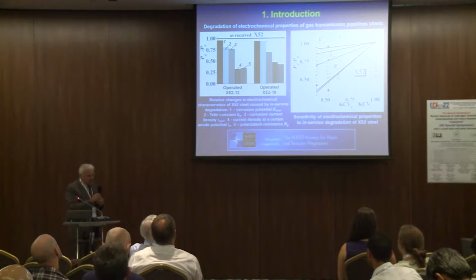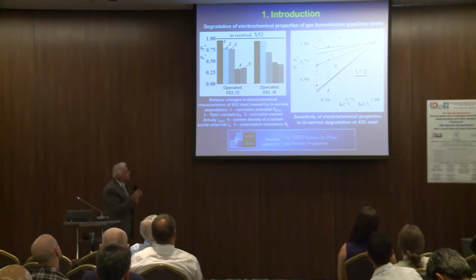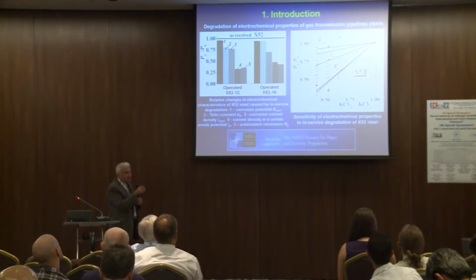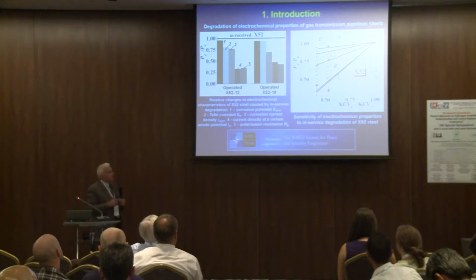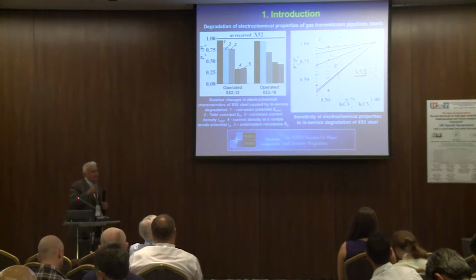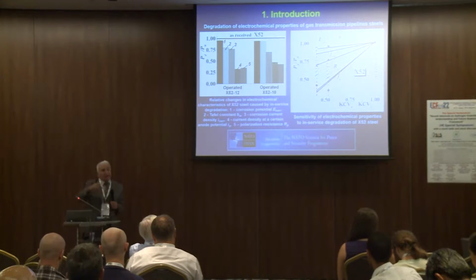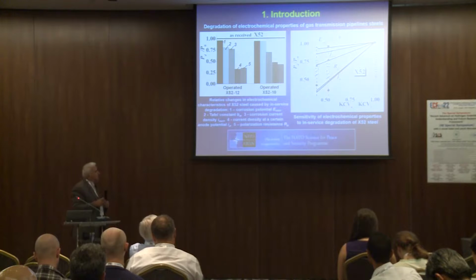For example, on the right side, you can see the change of polarization resistance. It is an electrochemical characteristic, and on the other hand, the change of impact strength. If you can measure electrochemical properties in field conditions, you can predict in some way impact strength without mechanical tests. It is the base for non-destructive evaluation or prediction of current mechanical properties.